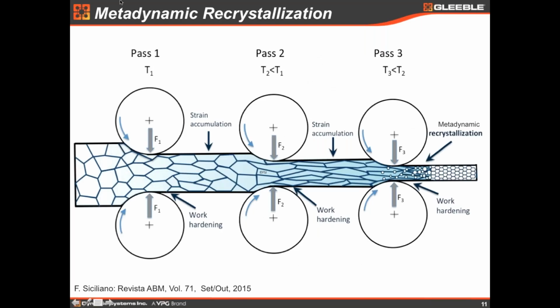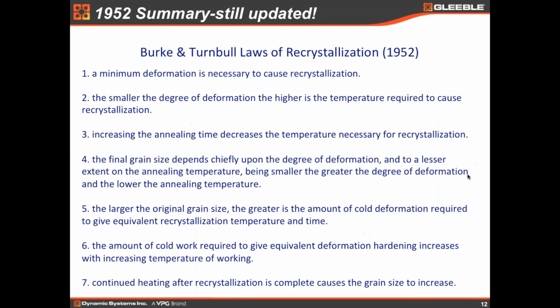We can see here metadynamic recrystallization, which is a very simple concept. We have strain accumulation in the passes, and at a certain time the accumulated strain is so high that we nucleate dynamic recrystallized grains in the deformation zone, and they grow as static recrystallization outside the deformation zone. So this is metadynamic or post-dynamic recrystallization. So we have dynamic inside and post-dynamic after that. So I think it's a very clear concept, no big deal.